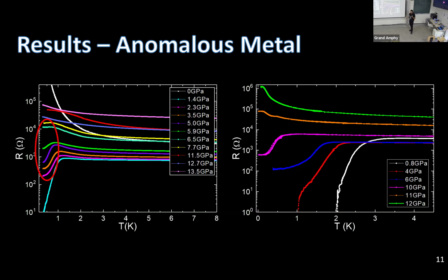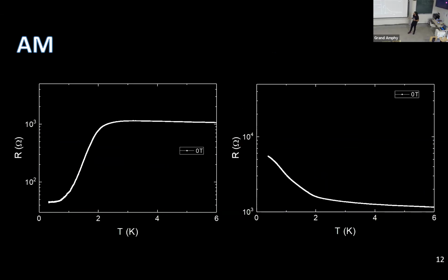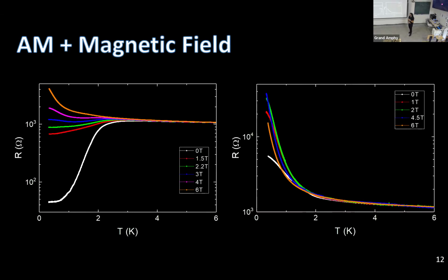Another thing that we did to make sure that this anomalous metallic state is real is to measure our indium oxide samples in 2 different labs, in Israel and here in France, and we saw this metallic state in both of them. And one last thing that we did is that we took our metallic phases, those 2 metallic phases, M1 with the resistance drop and M2, which is the start of the saturation, and added a magnetic field.